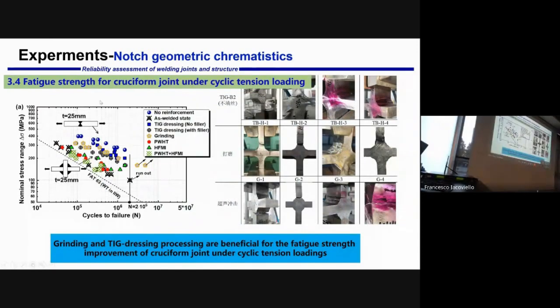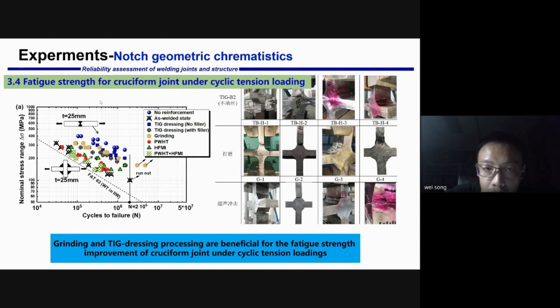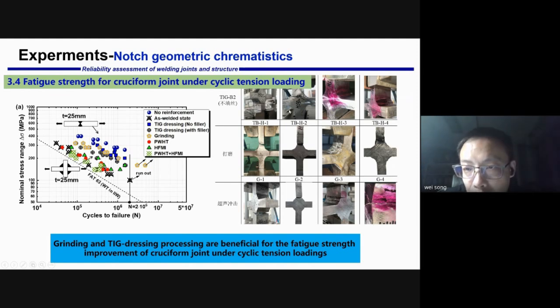Then we did the fatigue tests for the cruciform welded joint under cyclic tension loadings. From this result, we can see that the grinding and the TIG dressing processing are beneficial for the fatigue strength improvement of the cruciform joint under cyclic tension loading. As we can see from the right pictures, for the TIG dressing welded joint, the crack initiates from the weld joint, and for the peening or the grinding cruciform welded joint, it cracks near the base metal.